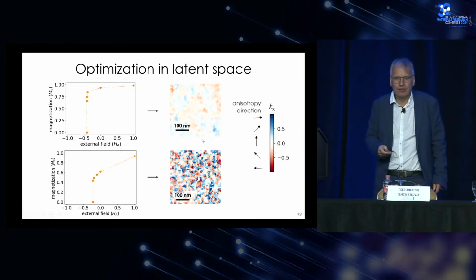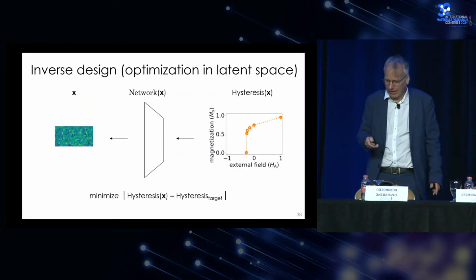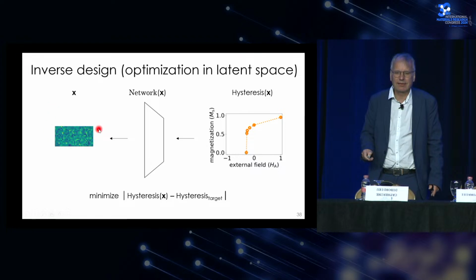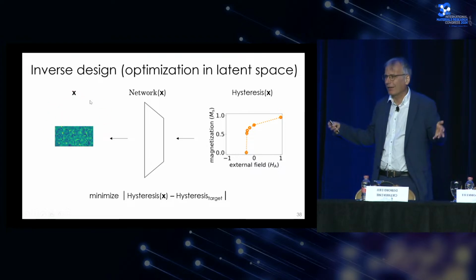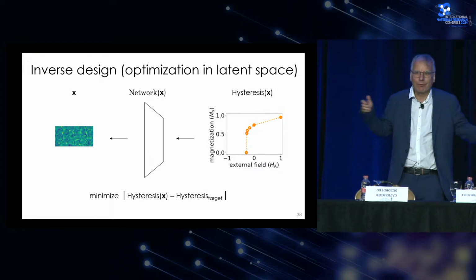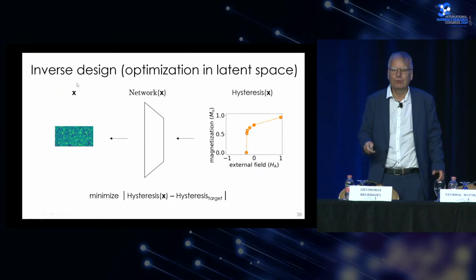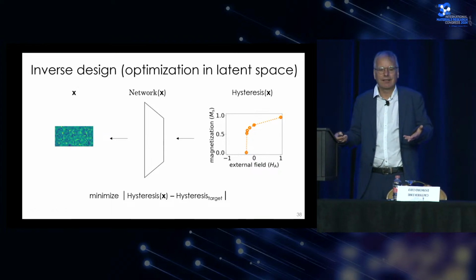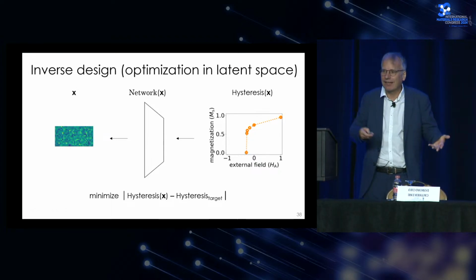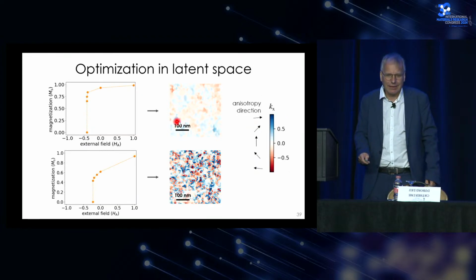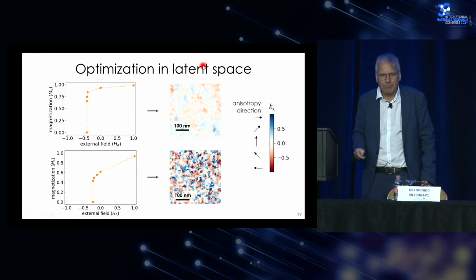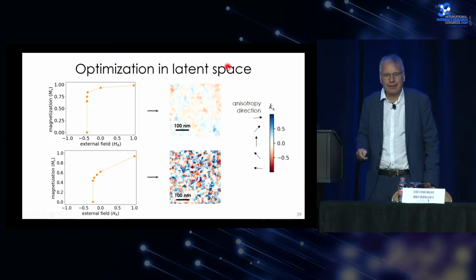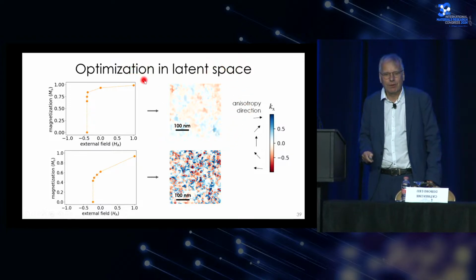So the idea is now that I have as input a certain demagnetization curve, I get as output the latent code of my granular structure, and because I have a one-to-one relation between the latent code and the granular structure, I now have an inverse design that, given an input for a certain demagnetization curve, gives me a microstructure that, if I'm able to realize this structure, will exactly create this demagnetization curve.